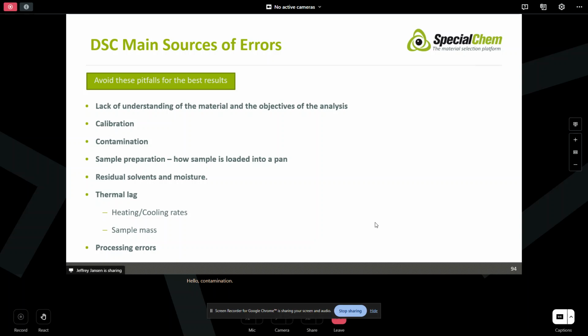Also, how you load the sample in, you don't want it to be one big nugget, if you will. You'd like it to make more contact with the bottom of the pan. Again, understand whether you have residual moisture or solvents in your material. Sometimes it's not possible to get rid of, but you need to understand then that they could interfere with that. Have a good concept of the thermal lag associated with the cooling and heating rate and the sample mass. And again, you're balancing resolution versus sensitivity there. Processing errors. Again, practice going over thermograms in order to look at that.